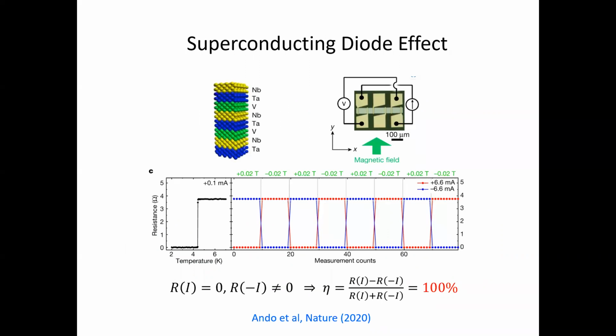So one of the recent experiments came from Japan 3 years ago. These authors were looking at superconductors. They created an artificial superlattice made of three layers of different superconducting materials: tantalum, niobium, and vanadium. This kind of ABC stacking creates an inversion asymmetric structure. Three is the minimum number you need to create inversion breaking in this stacking configuration. Moreover, they measured the IV characteristic in the presence of an applied external magnetic field. So now both time reversal symmetry and inversion symmetry are broken. And this material is a superconductor below around 4 Kelvin.